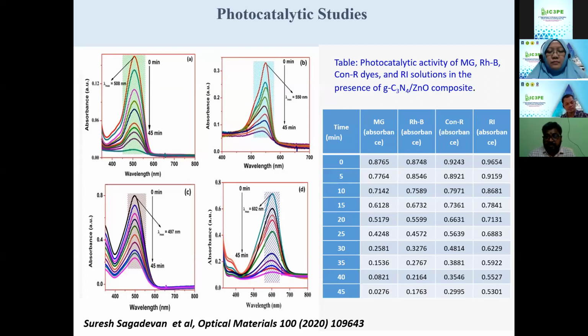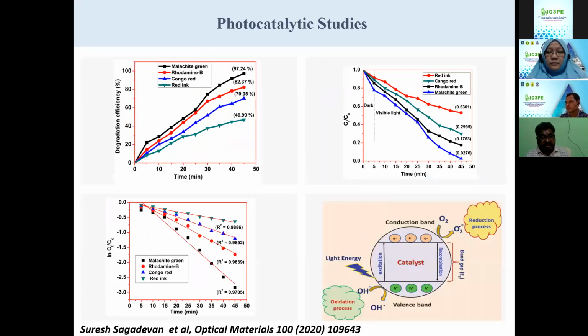You can see in the table, with respect to the different solutions, the RI solution only shows the highest value, 0.9654. And the photocatalytic degradation efficiency with respect to irradiation time, you can see here. From this graph, you can confirm that the malachite green shows higher efficiency. It is showing 97.24%, compared to the red ink solution.